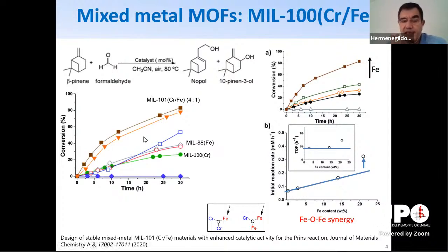In this slide, you can see the activity of different MOFs. One MOF is MIL-100 chromium, and the other has iron and has another structure. The point was to obtain MIL-100 with iron, because the prediction from theory is that this catalytic activity will be higher. But the problem is that it is not possible to obtain MIL-100 with iron, because then the structure collapses and you actually get this other MOF. So the point is, how can we have the advantage of the larger porosity of MIL-100, which is a very open pore MOF, together with stability and activity due to the iron?